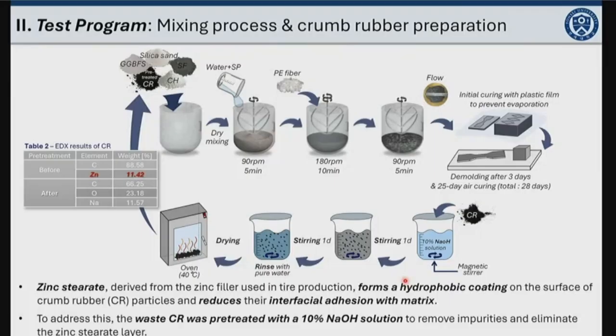According to the EDX result, the zinc was completely eliminated, while a small amount of hydrophilic sodium hydroxide was found to remain on the surface.